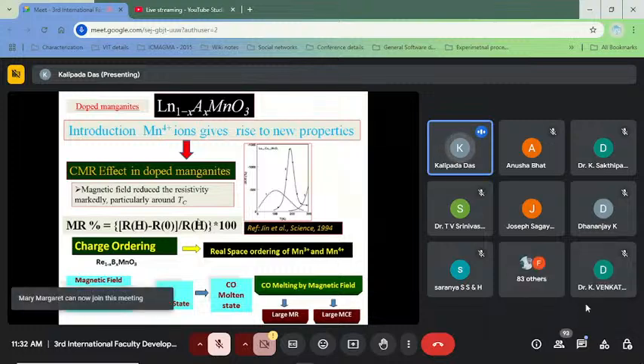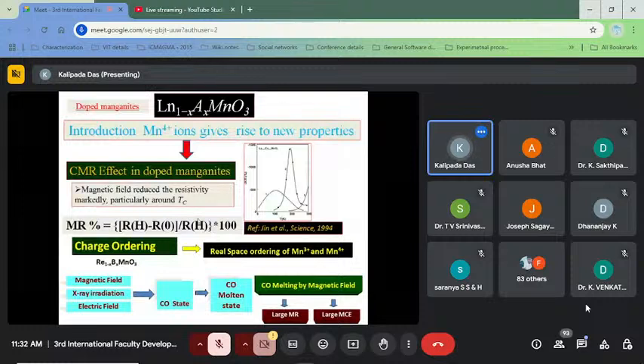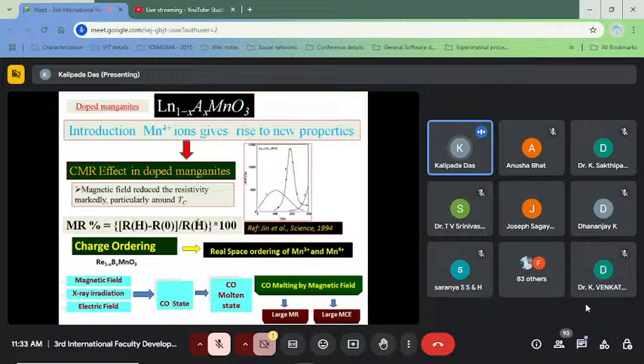Another fascinating property of that doped manganite, at nearly 50% doping, is the charge ordering. In the case of 50% doping, when there are 50% Mn3+ and 50% Mn4+ ions, then the Mn3+ and Mn4+ ions are arranged in a regular pattern. This is called charge ordering, and this charge ordering generally follows the antiferromagnetic type of ordering. But this ordering of the Mn ions can be melted by using a magnetic field, X-ray radiation, electric field, etc. And due to this molten state of the Mn3+ and Mn4+ ion ordering, we can get large MR and large MCE, magnetocaloric effect.